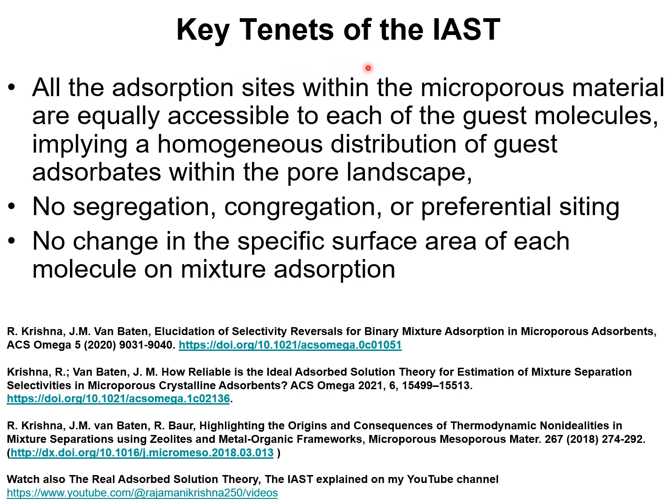We summarize the key assumptions that are made in development of the IAST. All the adsorption sites within the microporous crystalline material are equally accessible to each of the gas molecules, and this implies there is a homogeneous distribution of gas adsorbates within the pore landscape. There is no segregation, no congregation, or preferential siting of gas molecules within the pore topology.